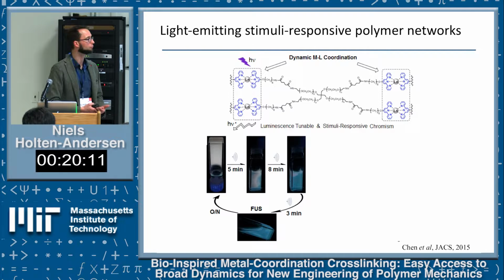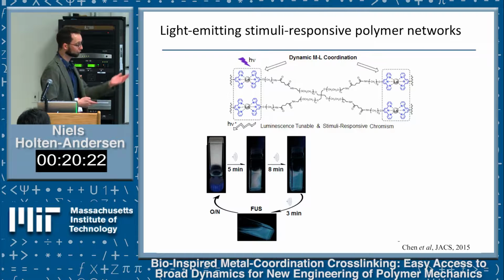Right now we're working with ExxonMobil on trying to actually use these for thin film coatings for strain, temperature, and stress sensing materials. We'll see if we can get it to work, but so far it looks pretty promising. This data shows that we can monitor the changes in the amount of bonds breaking in this region where we have the blue light emission.